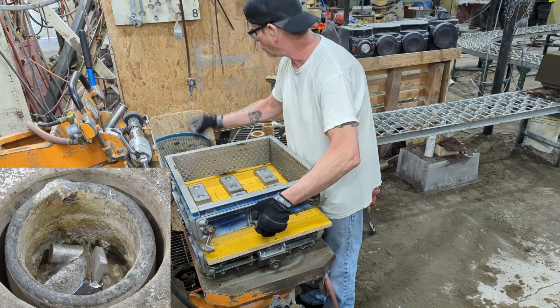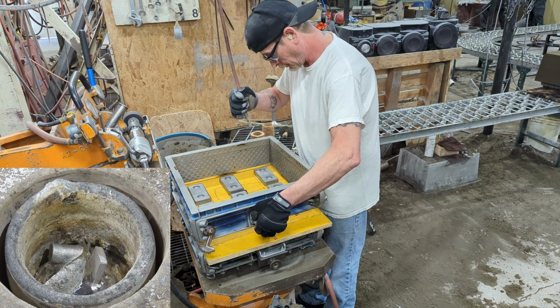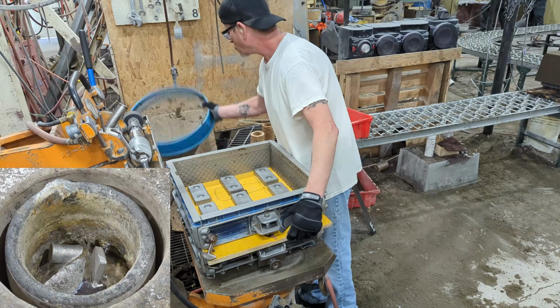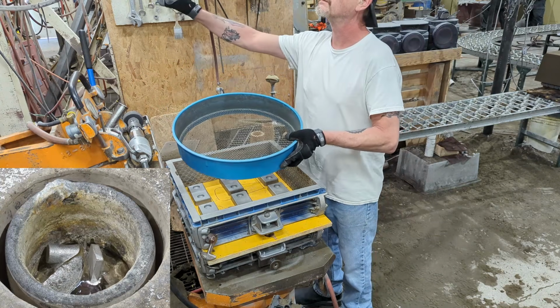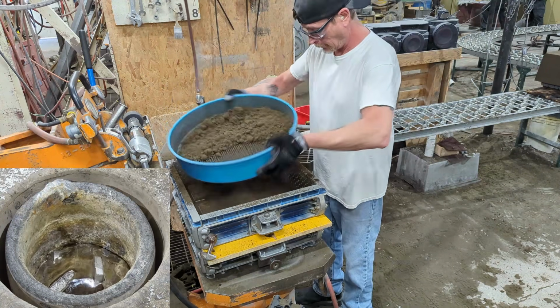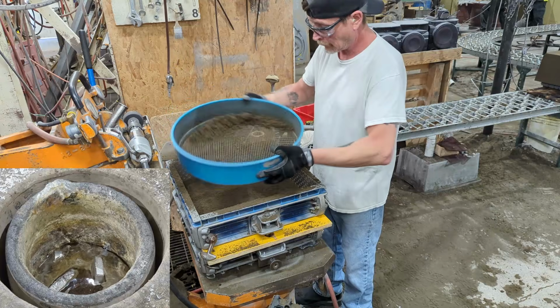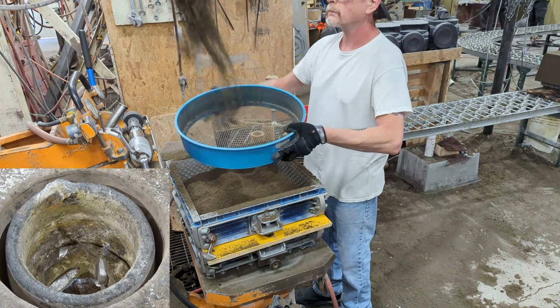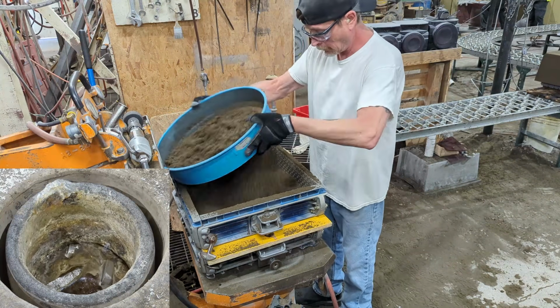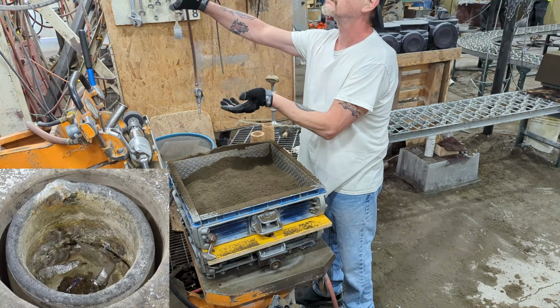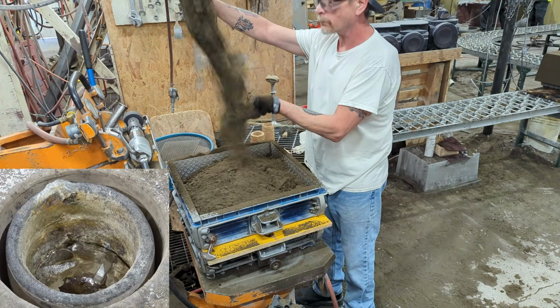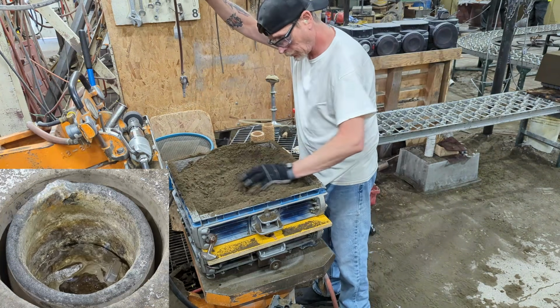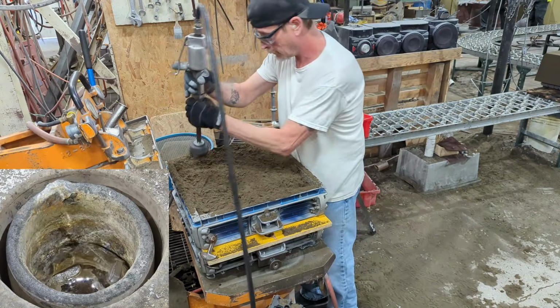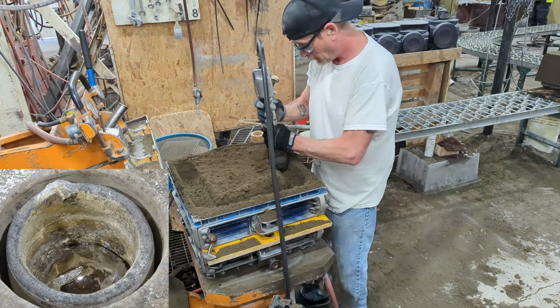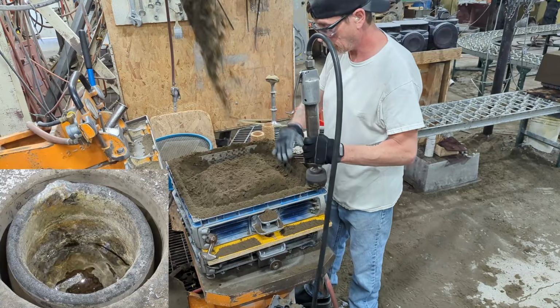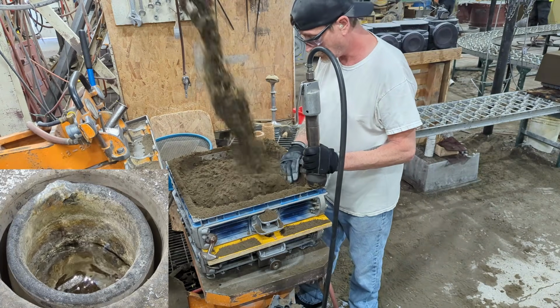Chad lifts his mold box, cleans out any loose sand from underneath it, and then uses a tool called a riddle, basically a fine mesh screen, to sift fresh, clean sand directly over his pattern. This gives us the best possible surface quality for the finished parts. He then fills the mold box with more sand and uses a pneumatic rammer, an air-powered compacting tool, to pack the sand tightly around the patterns. He repeats this several times to make sure the mold is firm and solid.